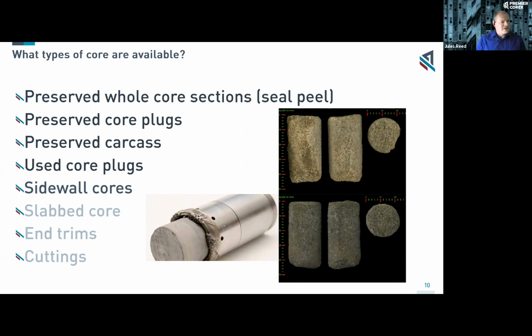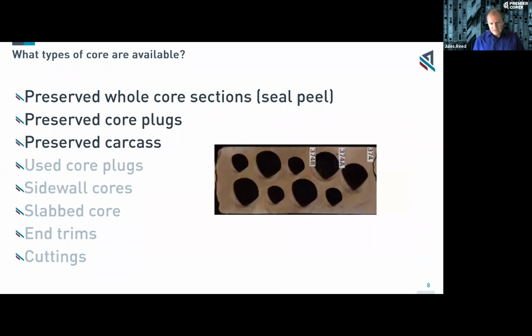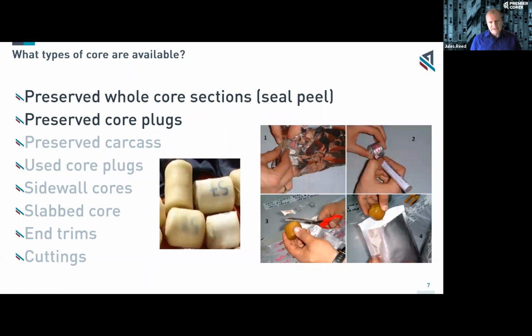Just one quick question that's come up. I use the term wax. This is not paraffin wax, is it? Is that still used anywhere? It's actually, I don't know the exact makeup of the wax. The wax that is used these days, which looks like this one here, this light colored wax, is a low temperature wax, so it's liquid at low temperature. So it's much safer. The old waxes used to have to be heated to 180 or 200 degrees. This wax, you can heat at maybe 40, 50 degrees. Part of the reason for using the aluminium foil and then the plastic wrap is to ensure that the wax isn't getting into the sample.